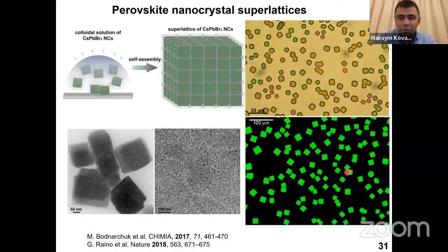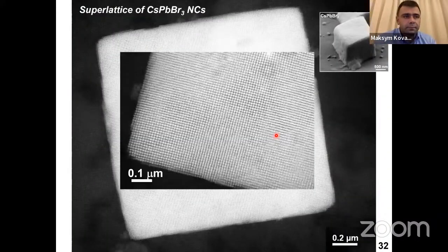Now you can ask, what about cubes? For cubes, it's much simpler. Cubes form supercubes, which is 100% space occupation. And so naturally, these were the first superlattices whose optical properties we examined at low temperatures. These large supercubes can be as large as 10, 20 micron, and they can be produced as single entities on the substrate. And this is electron microscopy of these.